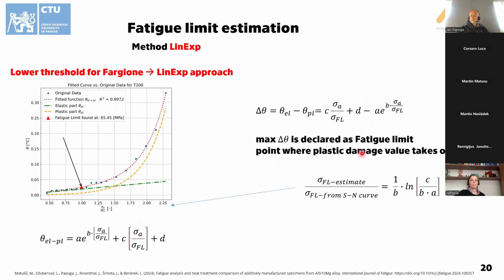However, we wanted to focus where the transition between the elastic part and the plastic part is visible. This is the ideal result, because we were trying to pinpoint the fatigue limit, and we are really close to it. And how we did it is really easy. We took the elastic part, as you can see here, and we subtracted the plastic part from it and found the maximum value of these differences. This is where we declare the fatigue limit, the point where the plastic damage value, in this case related to the stabilized temperature, takes over the linear evolution.